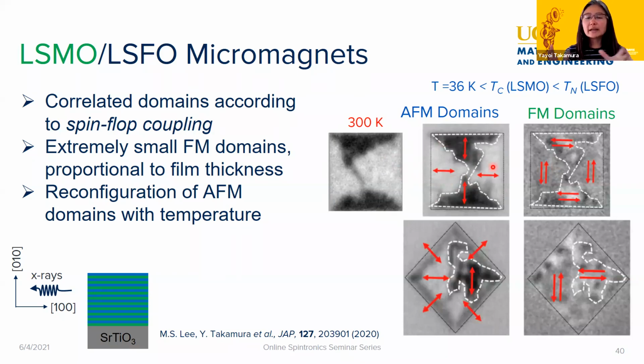So that actually means that antiferromagnetic domains can reconfigure, which is interesting because people say, oh, antiferromagnetic domains should be pinned at defects. But we can actually start moving them around with different conditions, as with the coupling with our ferromagnetic layer.